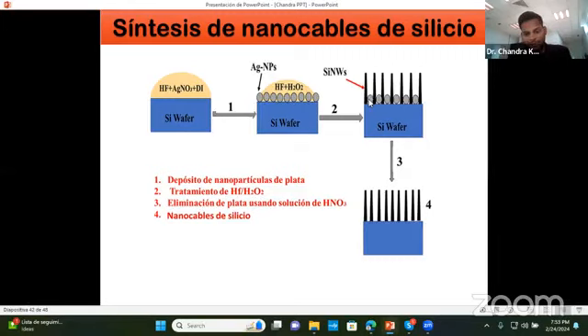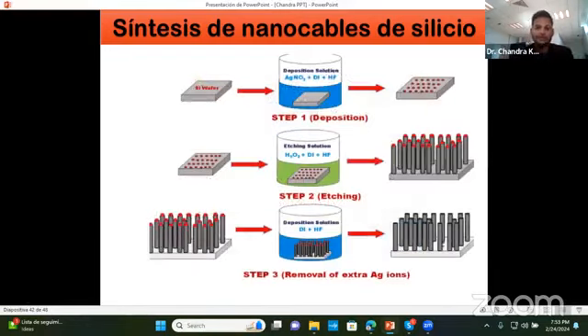This silver layer will reach here, and later we eliminate this silver layer using HNO3. Using HNO3, we can eliminate the silver layer from here, and later we can treat with HF to eliminate the oxide layer which is present on our substrate. Here, this is the more effective diagram.